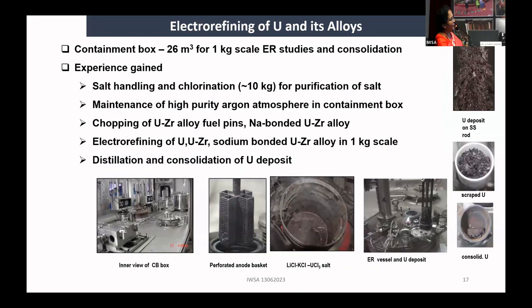Normally we take a double module glove box. This particular system, you can imagine, is a 26 meter cube containment box, which has all the facilities to handle highly sensitive, moisture-sensitive molten salt, and you are able to deposit uranium, recover uranium, induction melt it, and make it into uranium alloys.